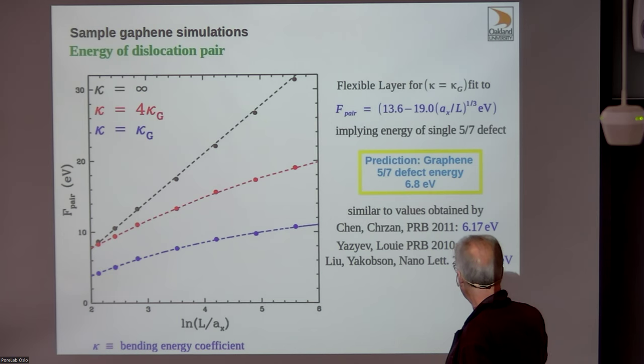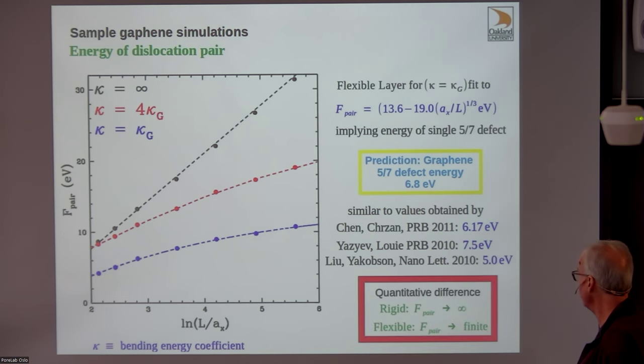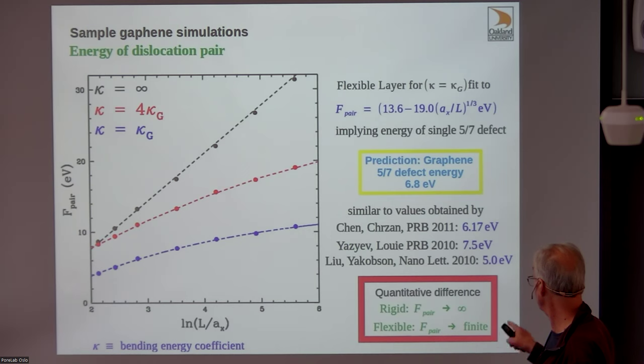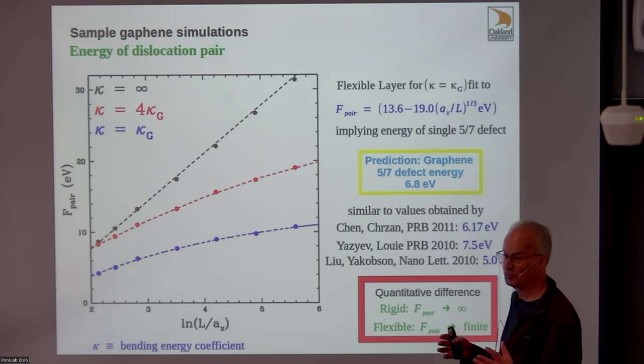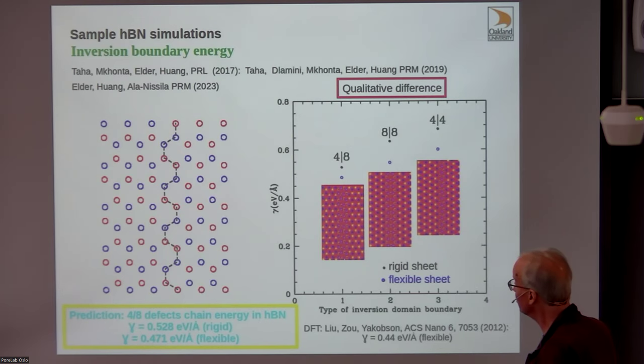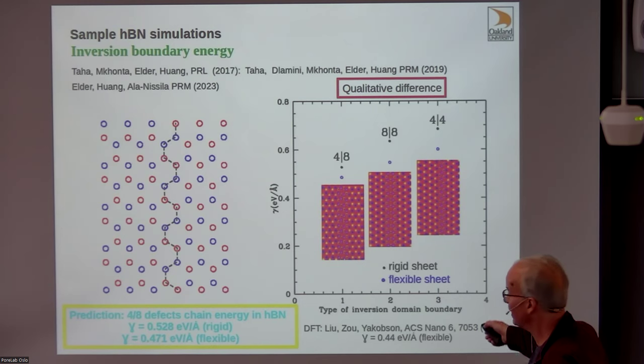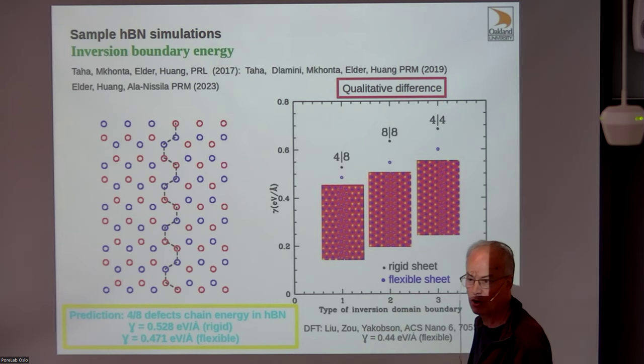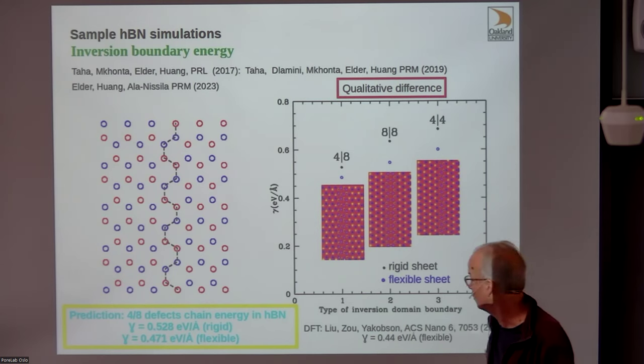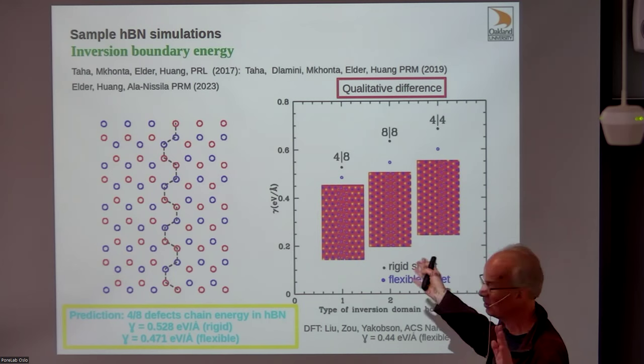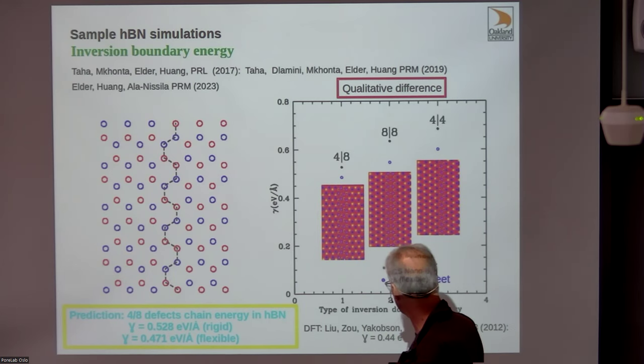By fitting the saturation and extrapolating to infinite system size, we can predict the energy of a 5-7 dislocation in graphene. We get 6.8 eV, which seems relatively consistent with other estimates. The key point is that the difference between rigid and flexible is not just quantitative but qualitative: one goes to infinity, the other is finite. For inversion boundaries in HBN, by contrast, they don't create long-range elastic fields, so flexibility lowers the energy by about 8–20%—significant, but not a qualitative change.